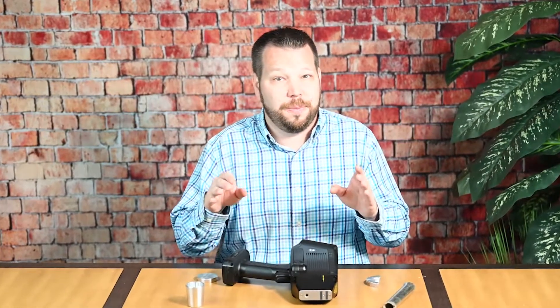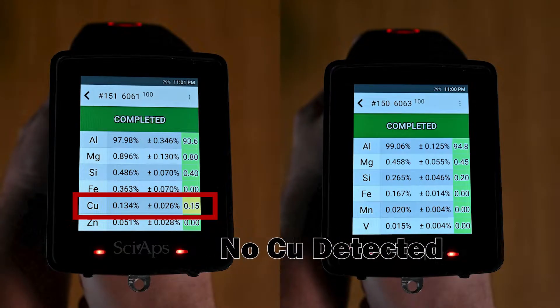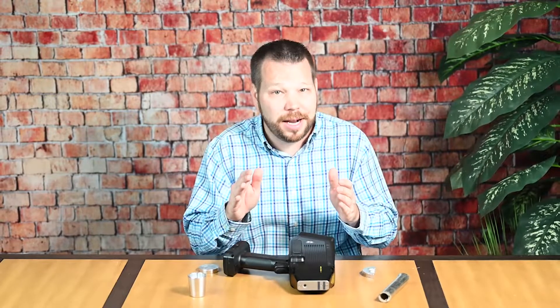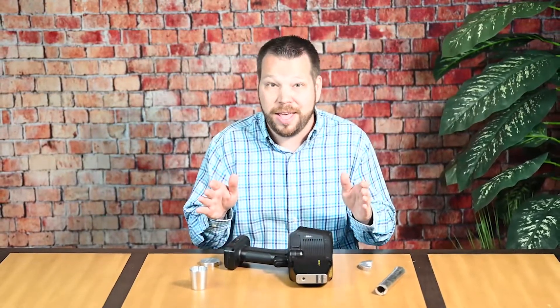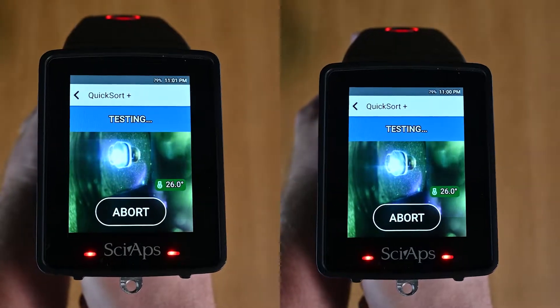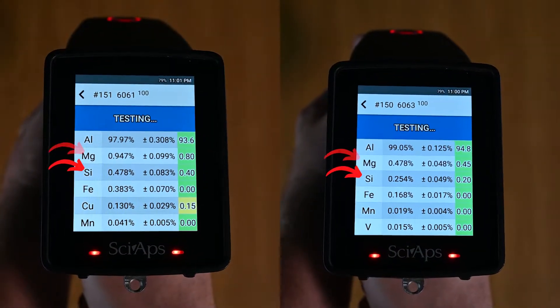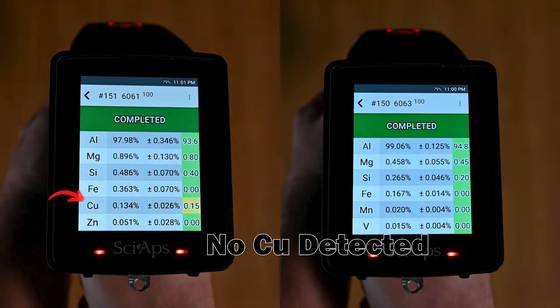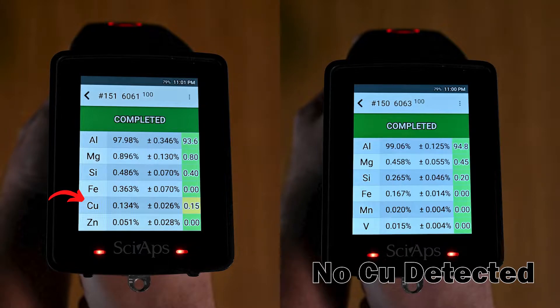Copper is our first big differentiator, being about 0.1% max for 6063, but having an intentional aim of 0.15% to 0.4% in 6061. Although copper is at a low concentration in these alloys, most handheld metal analyzers can consistently separate on copper alone. In fact, a lot of XRFs do this. In order to sort 6061 and 6063 effectively, we need silicon and magnesium to be in range for these alloys, and we need copper to be greater than about 0.15% for 6061 and less than 0.1% for 6063.